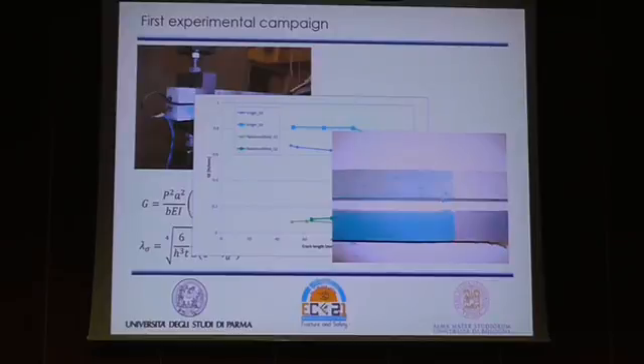Analyzing the fracture surface, it is possible to notice how part of the epoxy resin managed to pass through the nanomat and deposit itself on the adherent, initially in contact only with the nanomat. But a separation between the nanomat and the resin occurred. In fact, as you can see on the top adherent, the nanomat is discernible, while on the bottom adherent, the blue epoxy film occupied the whole surface almost without a visible trace of nanofibers.